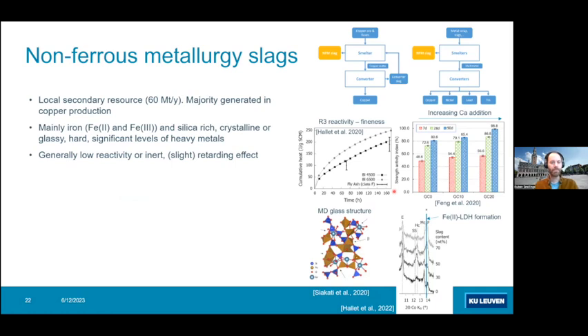Maybe to wrap up, a final one on the go. So a non-ferrous metallurgy slag, something we have been working a lot on in Leuven as well. So this is probably a more local secondary resource. We have a lot of it in Belgium. I suppose you also have some in Sweden. And the majority of this is generated in copper production. And it consists mainly of iron silicates. And in the regular form, it's a crystalline, hard material, for instance, used for abrasive properties. And as given, they are very lowly reactive or inert, and might even have some slight retarding effects.